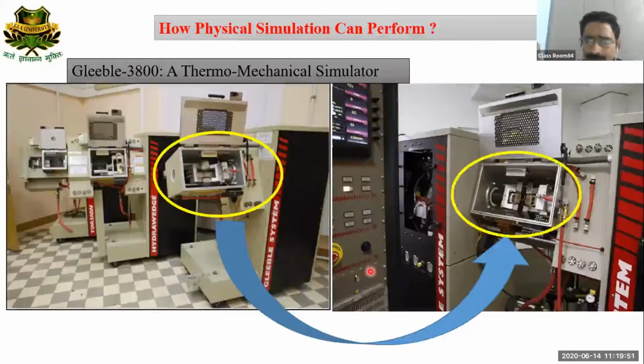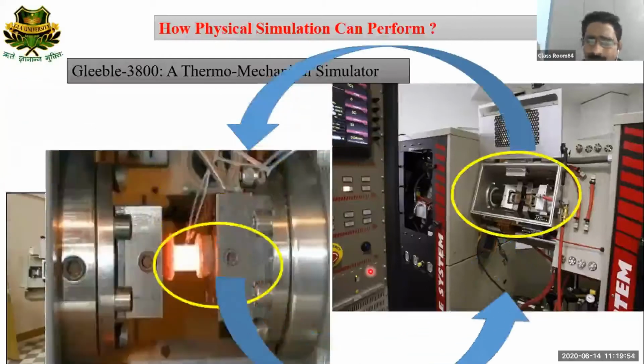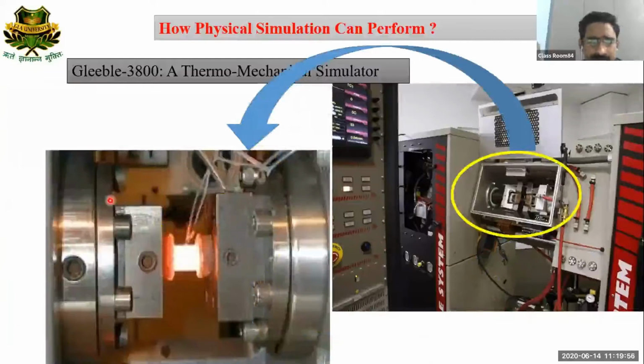So now, another expanded view of this working chamber. You can see the left side and right side both have jaws. And in between you can see the sample, which has dimensions of 10 mm in diameter and 15 mm in height, seeming just like a red hot rod. And just above, two wires are going. These two wires are known as thermocouples, which are already welded to the sample. It is a kind of spot welding.